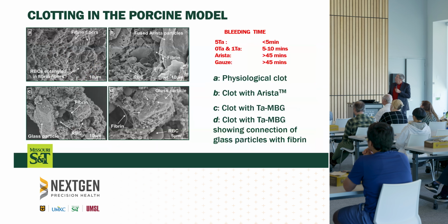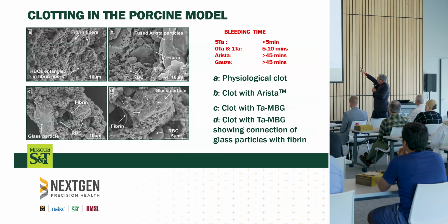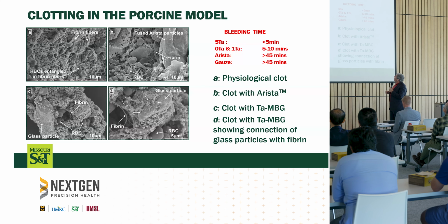What we saw then from that study is that when we looked at Arista, the bleeding time for that pig was just over 45 minutes. When we looked at applying a standard surgical gauze, so like a bandage, onto that wound on another pig, we found the bleeding time is again 45 minutes. That doesn't mean that the gauze or the Arista stops bleeding in 45 minutes. That means the pig bled out in 45 minutes. Those two interventions were wholly ineffective.